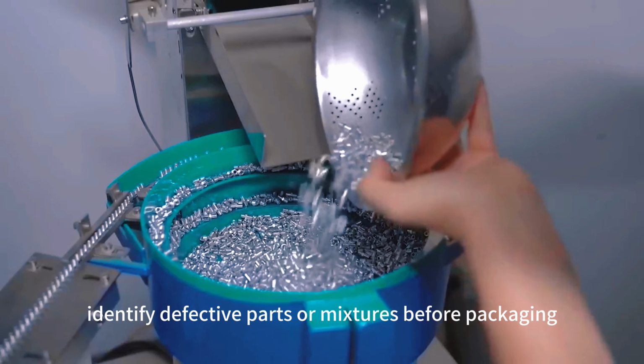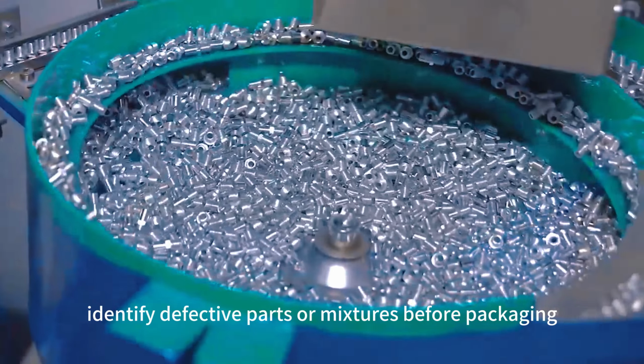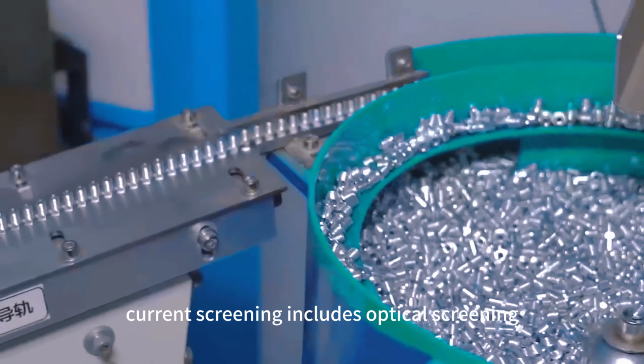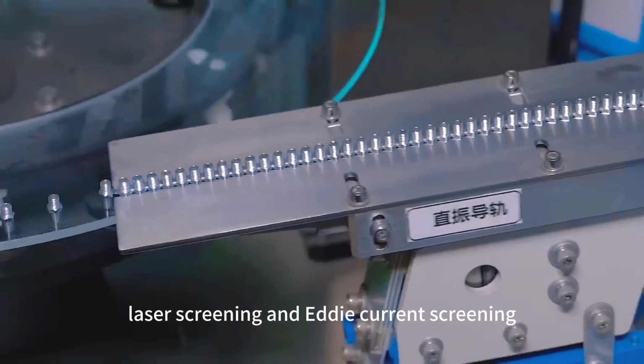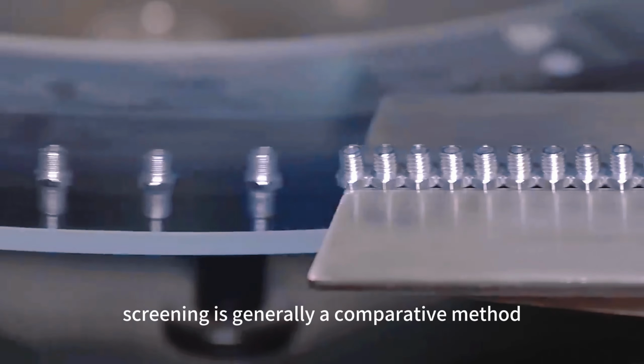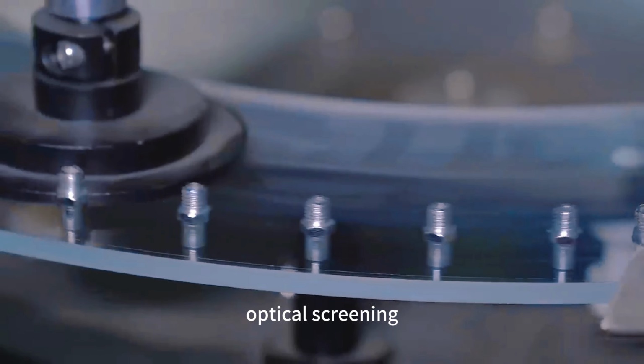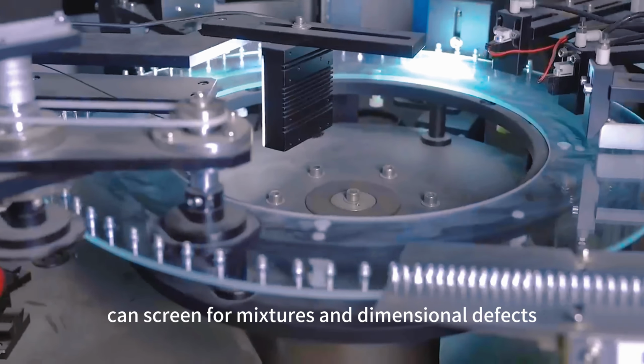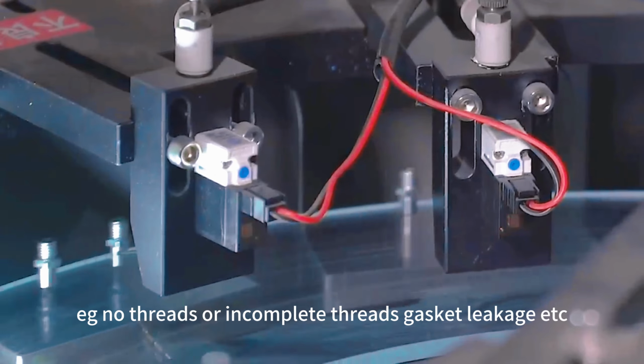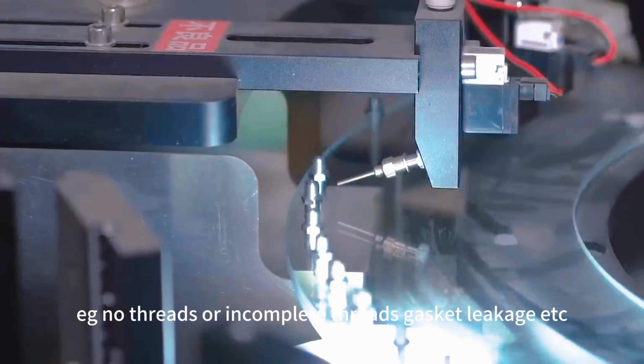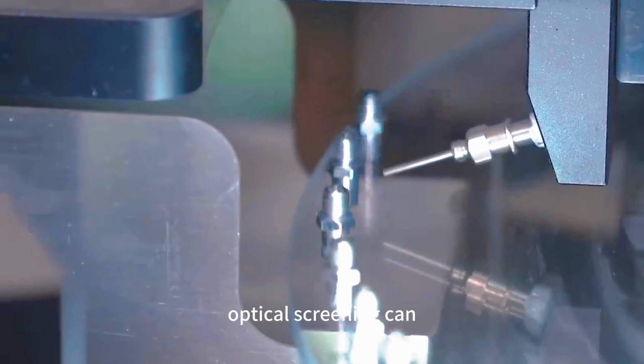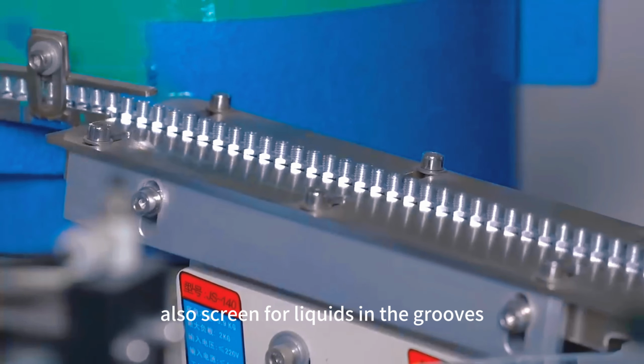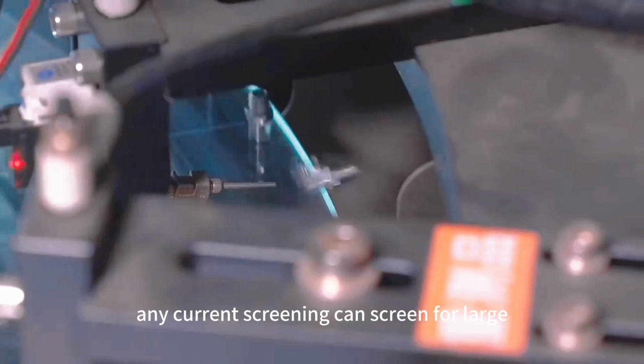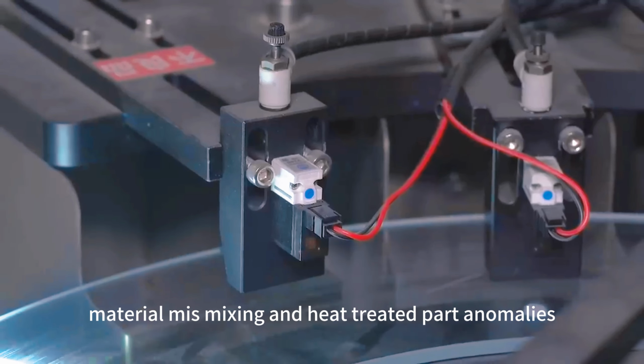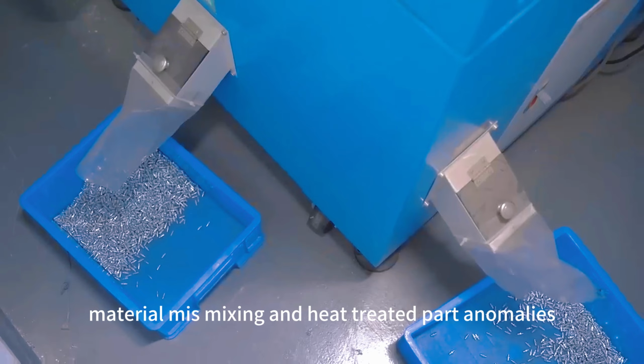Screening. Finished bolts need to be screened to identify defective parts or mixtures before packaging. Current screening includes optical screening, laser screening and eddy current screening. Screening is generally a comparative method. Optical screening and laser screening can screen for mixtures and dimensional defects, e.g. no threads or incomplete threads, missing washers, etc. Optical screening can also screen for liquids in the grooves. Eddy current screening can screen for large hardness deviations, material mixing and heat-treated part anomalies.